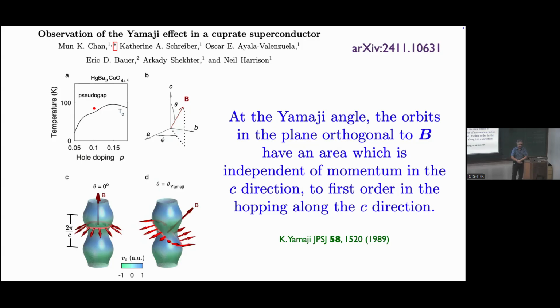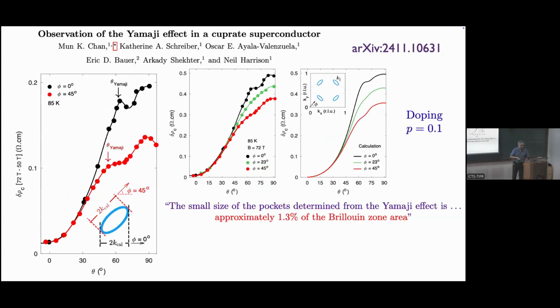The amazing thing is that if you measure the Yamaji angle, you can read off the size of the Fermi surface. It doesn't depend on any modeling. All you need to know is the Yamaji angle and the spacing between the layers, the value of C, which you know to high accuracy. And that will give you the area of the Fermi pocket. So this is what they reported. They assumed an elliptical pocket.